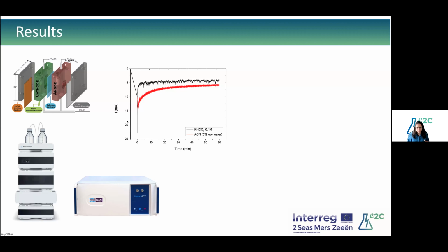In this specific graph, you have two lines, a black and a red one. The black one is the standard benchmark electrolyte that's used. If you look in literature, most of the literature for CO2 reduction is working on 0.1 molar bicarbonate, sometimes a little bit more concentrated, sometimes a little less. And we have in red the electrolyte that we are proposing. This is one of the mixtures that we're proposing. We're still looking into the research, but we already see an increase in the current densities. So this is an advantage to the system.